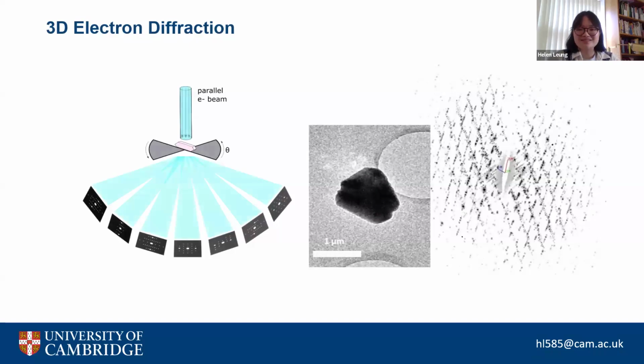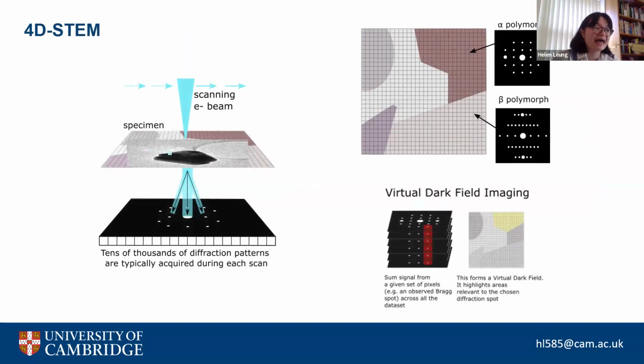Okay, so coming back to our 3D electron diffraction, we've looked at the insights of this data. We've realized there's another polytype. What can we do now? Well, because we only are looking at such a large area, illuminating our area, the obvious thing to do is to turn to 4D STEM. So in 4D STEM now, we're looking at a much smaller area in our crystal because we're illuminating a much smaller area. I think our step size was maybe about 5 nanometers. And with this, we're getting structural information, but at higher spatial resolutions. And so the idea is maybe now we can separate form 1 and form 2 from within the same particle.